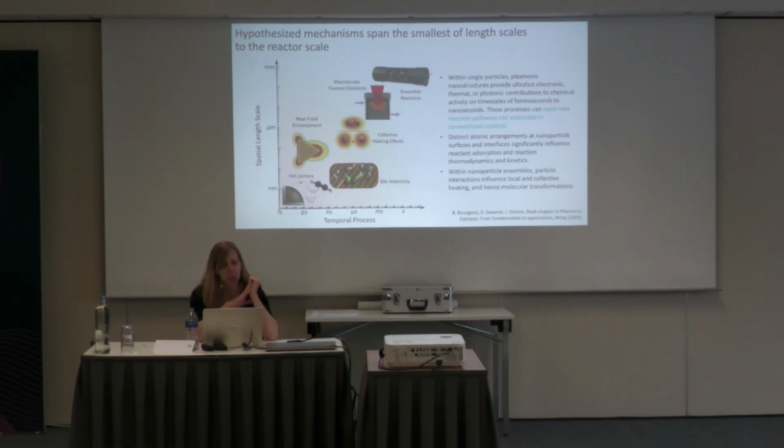The main reason we've mostly worked with the metallic nanoparticles is because they have generally more catalytic activity, so they're more chemically reactive than the dielectrics, which tend to not have the same sorts of tunability over the site selectivity and the formation of those hybrid orbitals that you need for catalysis.